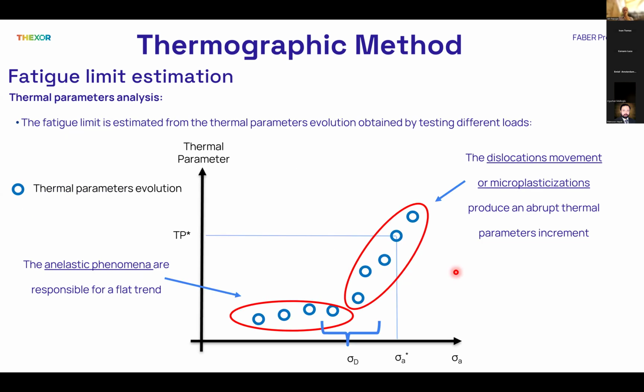Then the fatigue limit is estimated by analyzing the thermal parameters' evolution as a function of the stress amplitude adopted during the fatigue test. The fatigue tests are interrupted when an abrupt thermal parameters increment is detected during this evolution. Each of these circles corresponds to a certain thermal parameter calculated from the thermal profile obtained during a certain fatigue test with a certain stress amplitude.